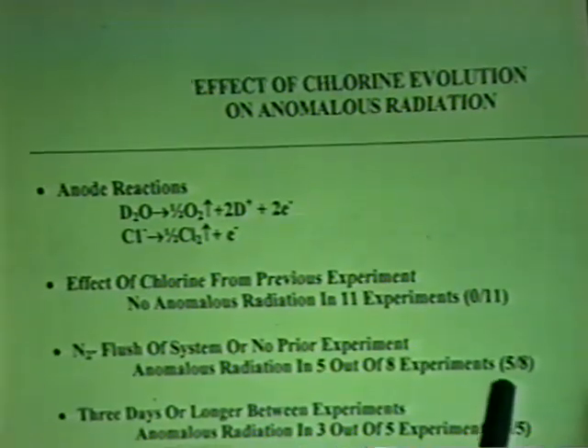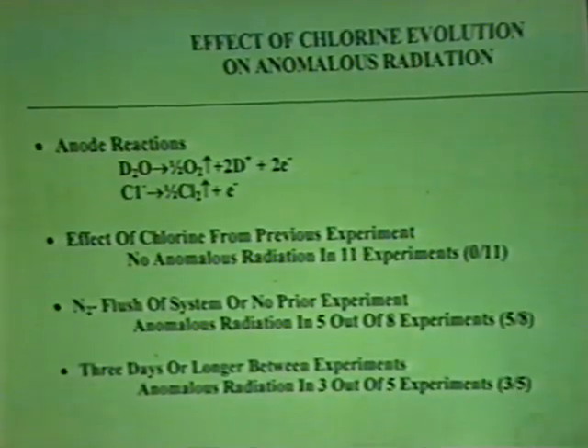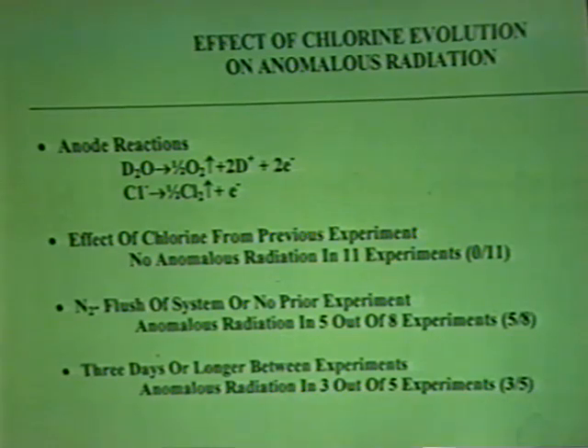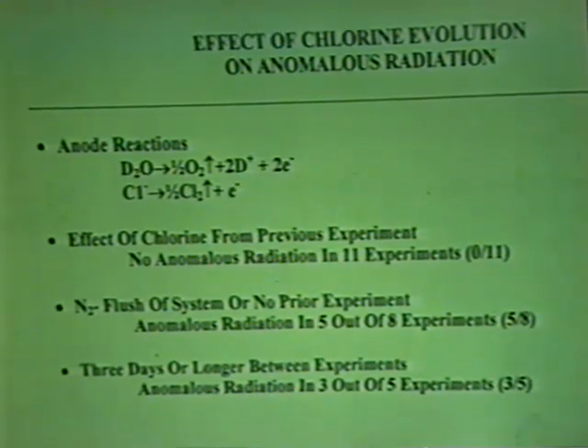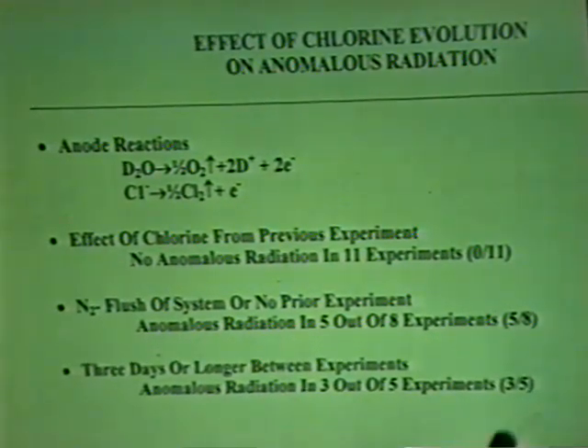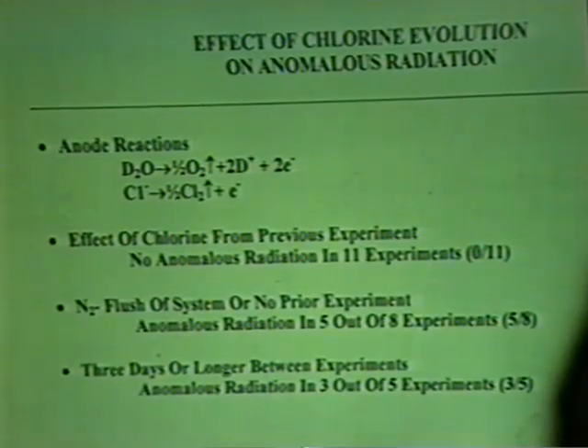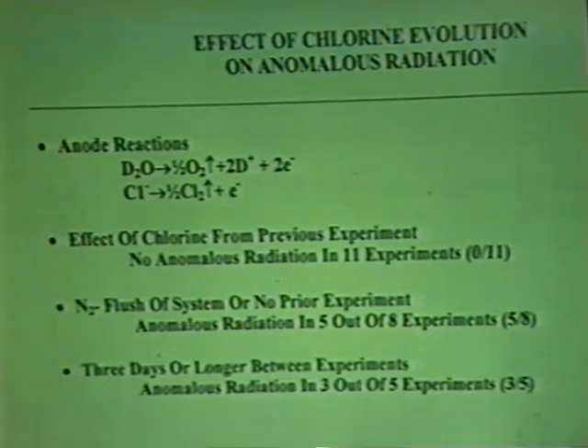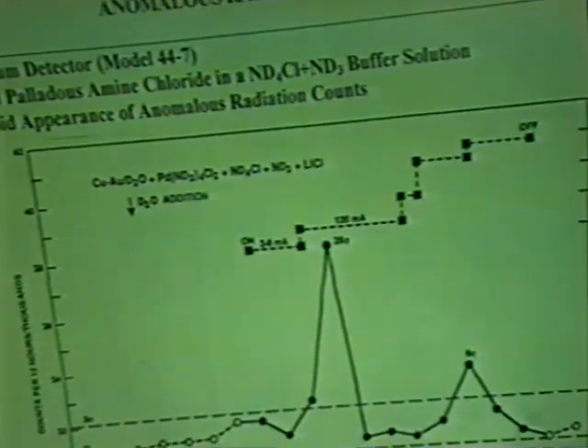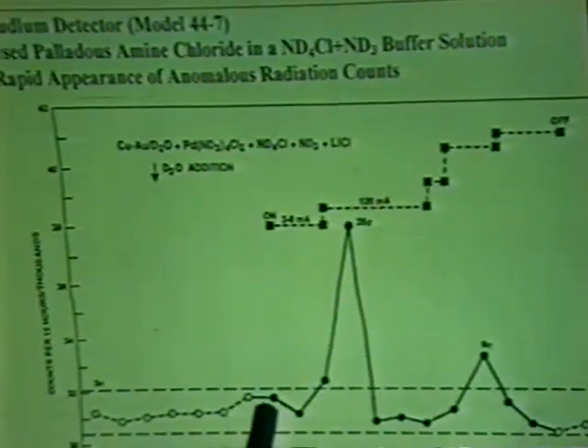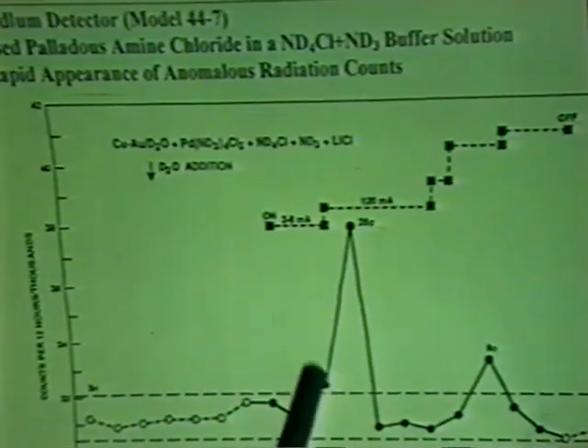When we flushed out the system with nitrogen, we saw this 5 times out of 8. Or if we didn't rush the experiments and took our time and set another experiment up 3 or 4 days later, then we got this effect 3 out of 5 times. So it seems like it is definitely related to chlorine being in the system when we start the reaction. This is another example where we had normal counts, we turn on the current, and then we got a large peak right here of radiation counts.